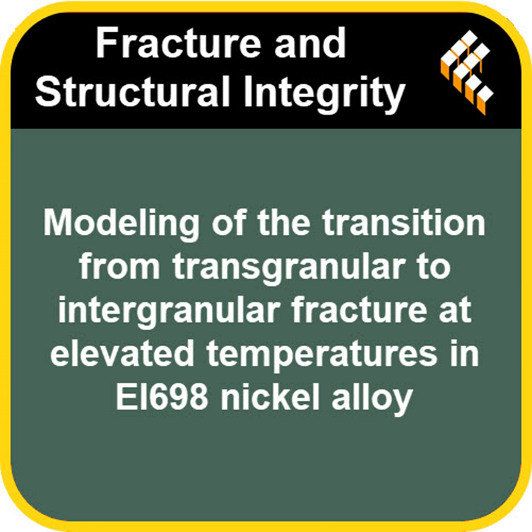That's powerful. It is. And digging into the nuances a bit more, remember that plastic energy dissipation. The model showed that needing about 90% of that plastic energy to dissipate as heat was crucial for getting the macro crack growth plane right, matching experimental observations, comparing figure 9a and 9b. This really demonstrates the model's ability to capture the complex interplay between plastic deformation and actual fracture propagation. It's not just breaking, it's bending and breaking. Right, getting that balance correct is key.